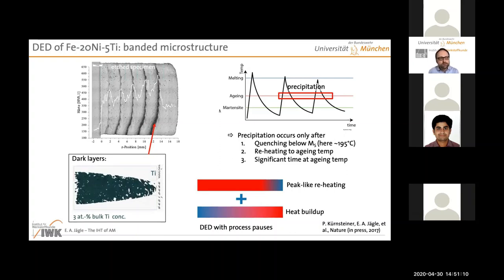In DED, we don't really use a powder mixture in the sense that we use two powders and mix them together and then do the process. But we use these two different feeders. So the machine has one feeder here and one feeder there, and you have two tubes going into the machine. And at some point, there's a swirl chamber where the two powder streams are mixed, and then that is fed into the melt pool. So in the case of DED, we are doing this, and that works really well.